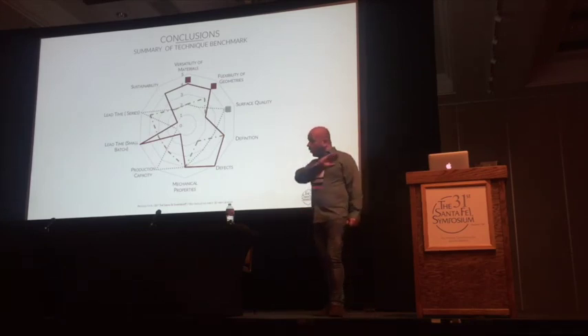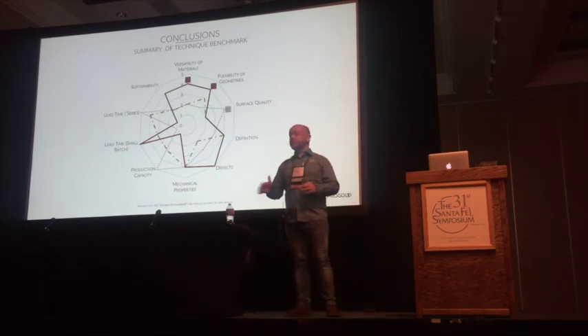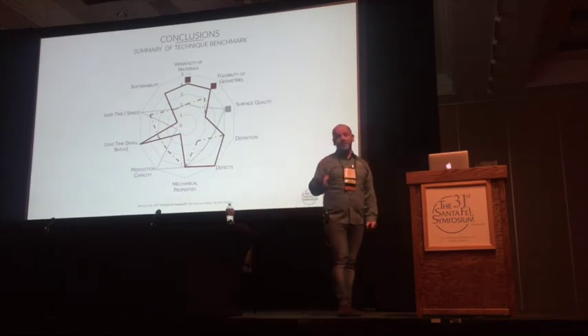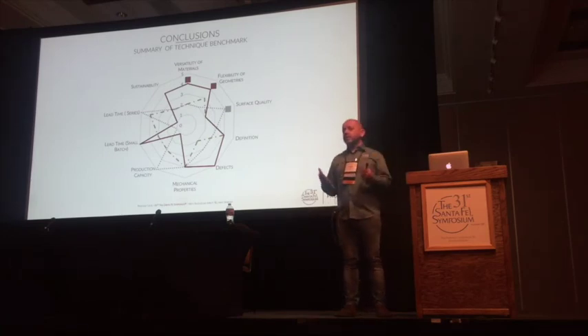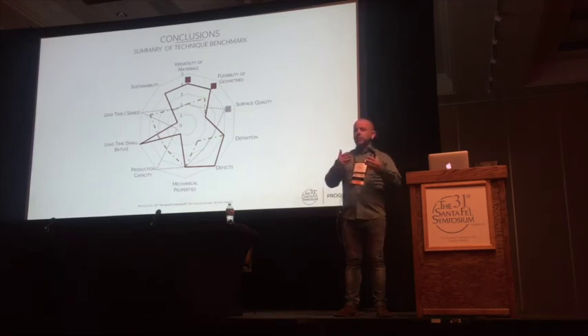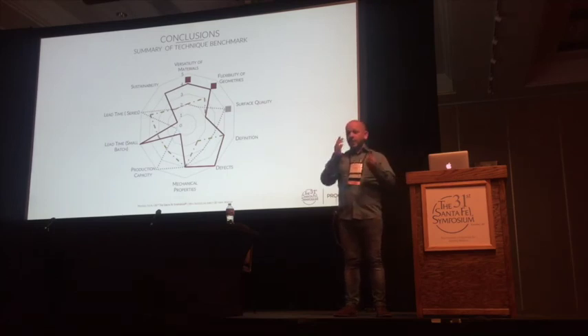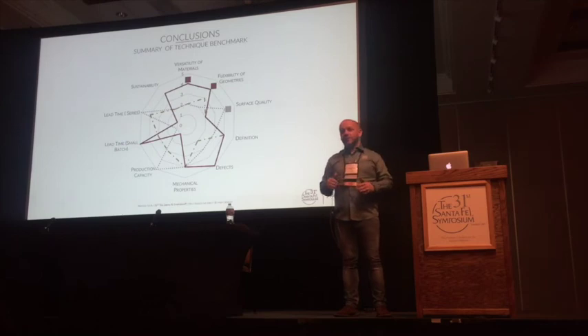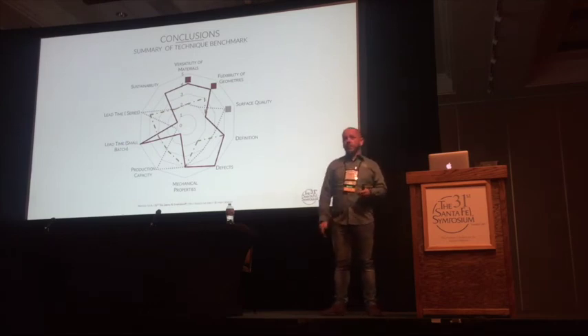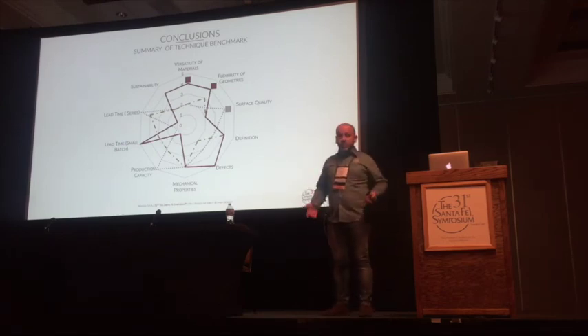The surface quality always, in terms of roughness, traditional casting is still the best. We have a chance to improve, but at the moment, I mean, having a big power laser, having a spot much smaller, being able to make a trace much thinner, having powder flow instead, like the one we were using, from 0 up to 50 micron, have the cut 10, 20 micron, then for sure the roughness is going down drastically. But it takes time to really investigate.